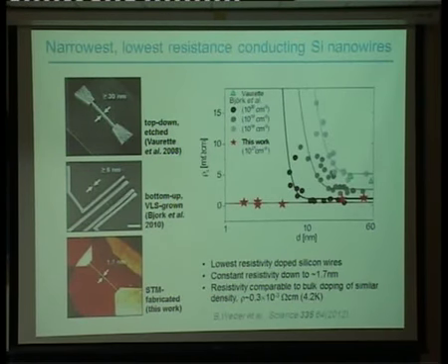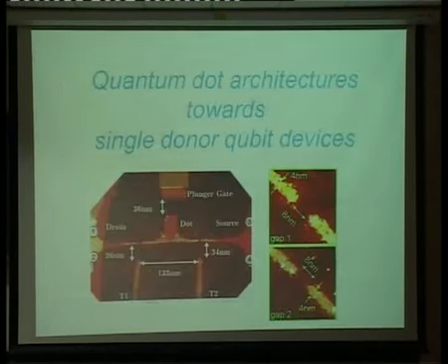So basically, you don't deactivate the carriers as you do in the other kind of freestanding nanowires that are out there. The phosphorus probably are ordered also. So they're not completely ordered. There is some ordering, but they're not completely. So basically it's a gaseous chemical reaction. So you can't actually put them down unless you create holes to put them exactly in position, which is something that you can do. So this, I guess, was a very interesting result. It basically shows us that we can make these wires very, very thin and bring them in towards our single atom qubit states to address them.